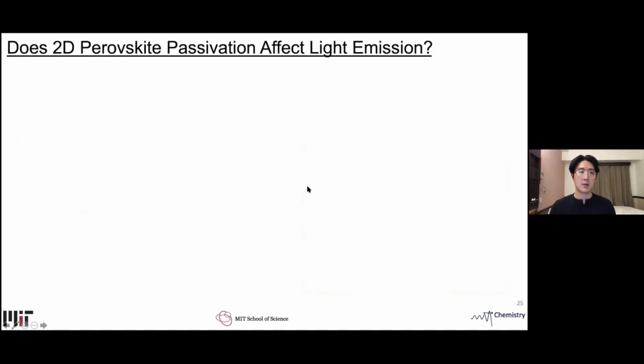Also encouraged by the high open circuit voltage, we decided to characterize its electroluminescence efficiency, which is relevant for many reasons. Eli Yablonovich, a professor at UC Berkeley, has once said a great solar cell has to be a great LED, because an open circuit voltage is related to its radiative efficiency, and the radiative efficiency is also related to the efficiency of the electroluminescence.